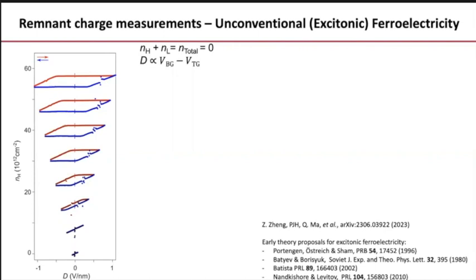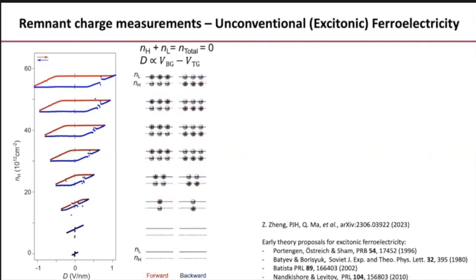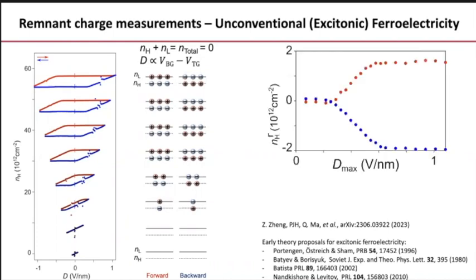In a regular ferroelectric, the whole structure changes. There's a structural transition, and your electric dipole moment goes from, let's say, up to down, all of it. In this structure, we're adding these dipolar excitons continuously. And as a result, we can get any size of hysteresis loop that we want. This is a ferroelectric with a continuously tunable electric dipole moment. We can study this as a function of displacement field.